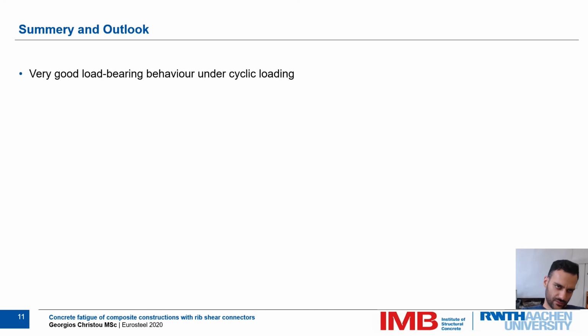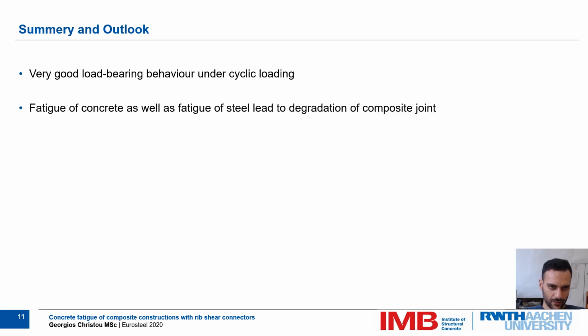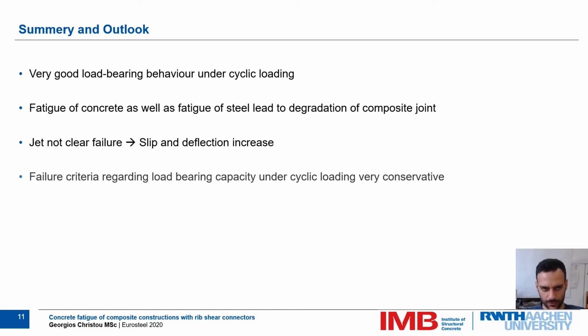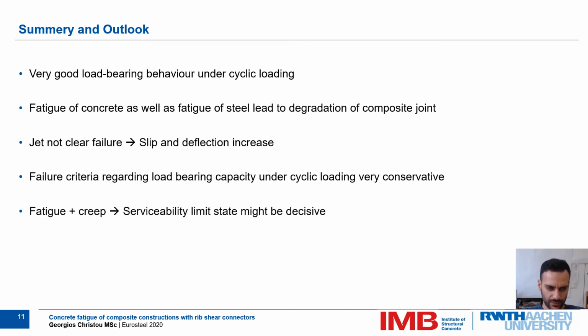In summary, we have seen a very good load-bearing behavior under the cyclic loading. We could not observe any failure. Fatigue of concrete as well as fatigue of steel lead to degradation of the composite joint. Yet we did not have a clear failure besides slip and deflection increase. The failure criteria regarding load-bearing capacity under cyclic loading in the current technical approval are very conservative, and fatigue together with creep might lead to serviceability limit state being decisive.